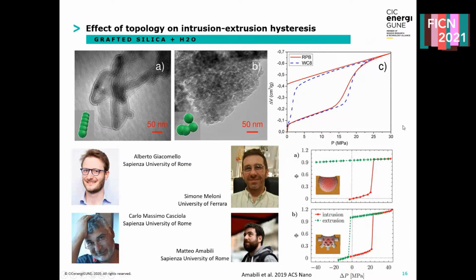So hysteresis in the intrusion-extrusion process, as you can see, is very important because basically it defines the energy pool for the electrical energy to be generated. So therefore we put quite a lot of attention on investigating the intrusion-extrusion hysteresis. For example, you have already seen some of these results during this workshop presented by Simone.